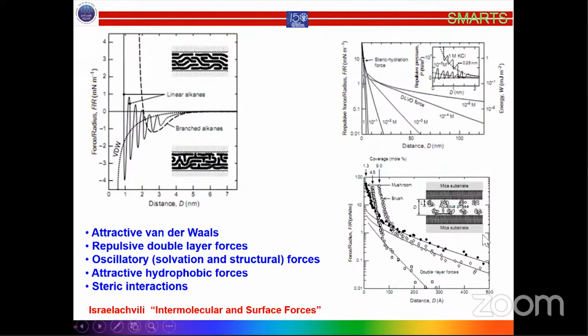And the beauty is you can also functionalize the surfaces with macromolecules and see how they interact and how the forces vary as a function of distance. You see, it is from 150 nanometers down to a nanometer. You can bring them together and get the forces. You can study the hydrophobic and hydrophilic interaction, as demonstrated here, and the steric interaction. All these things were done between the 70s and 90s. It has a lot of relevance with respect to stability of systems, lubrication, wear, and tribology.